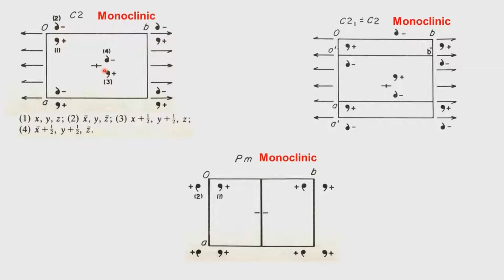This is not an equivalent point which is generated by the symmetry operation. So, the additional symmetry which we have got from the centering should also see the symmetry operation. In order to be consistent with the definition of the space group, we have to have the closure property, and therefore this point number 3 will also see the two-fold axis, which is now generated automatically at half position, because we have a two-fold at 0, we have a two-fold at a half position, and we will generate another two-fold. So, this two-fold will take object 3 onto object 4.